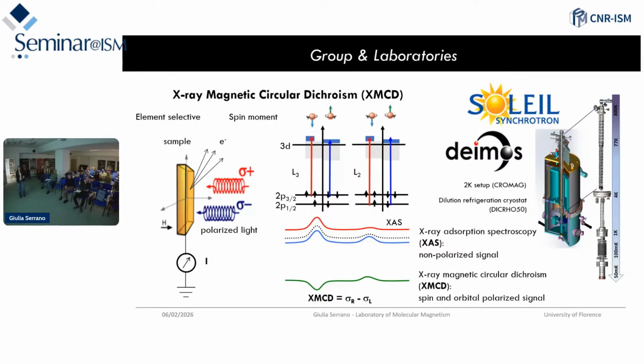Of course, you can do that in the presence of a magnetic field directed perpendicular to the surface, and at very low temperature, nominally 2K if we use the CROMAG setup, but we can also go with the dilution refrigeration cryostat to the sub-K regime, so down to 200 mK nominally.